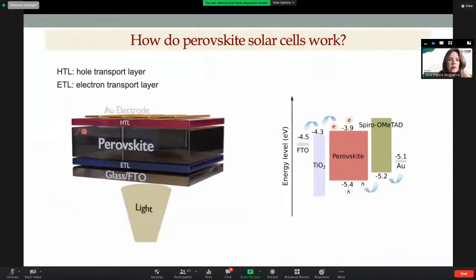Well, how do perovskite solar cells work? This is an example. The perovskite is a semiconductor. This is the energy level between the electron and the hole transport materials. When you shine light, you create free electrons and holes. The electrons are transported through the electron transport layer to the FTO, which is our transparent contact. And the holes move up through the spiro, the most traditional hole transport material, an organic molecule, to the gold contact. This is the most traditional structure for a perovskite. Then we have voltage and current. Remember that voltage times current means power.